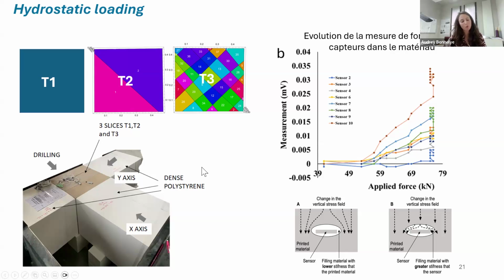And we've been trying to work on how to insert some sensors, because when you have a big machine and just sensors outside, you don't really know what's happening inside, and what we are interested in is what's going on inside. So we've been inserting some force sensors inside of the material in order to see whether they can measure something. And actually they do measure something. All of those curves are showing the evolution, as a function of the applied force, of the measurement inside of the sensors.